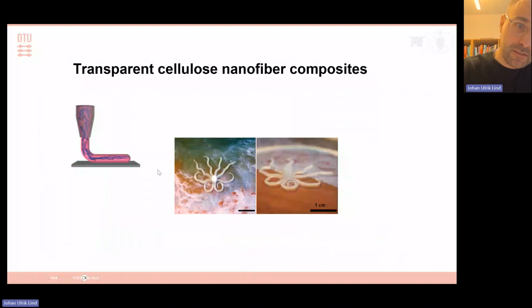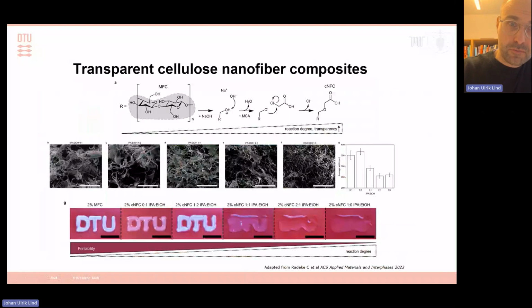So the first challenge here for us was to formulate some nanofibers that remained fibrillar, but were transparent. So what we turned to was a very classical reaction, which is carboxymethylation, where you carboxymethylate the side chains of the cellulose. And what that does is it makes it more hydrophilic. It also kind of etches down the size of the fibers. So as we increase the degree of reaction, we get an average fiber width decreased from, say, 350 to about 250 nanometers. And the way we tune that, which is kind of a detail, is actually by the choice of solvent instead of the reactants.